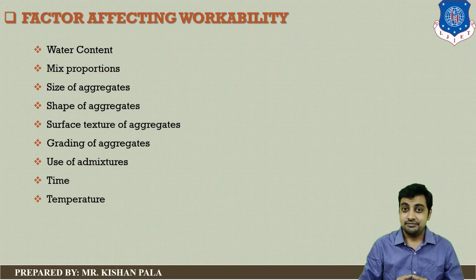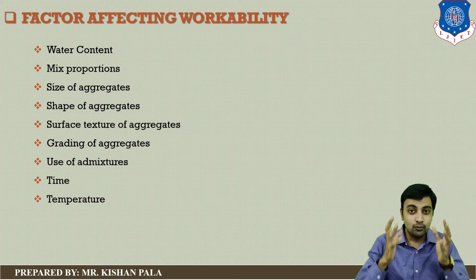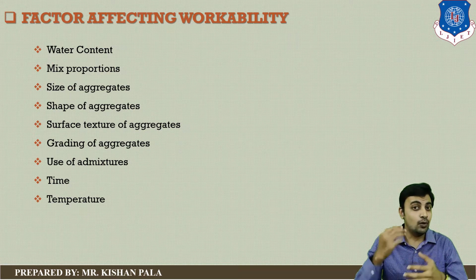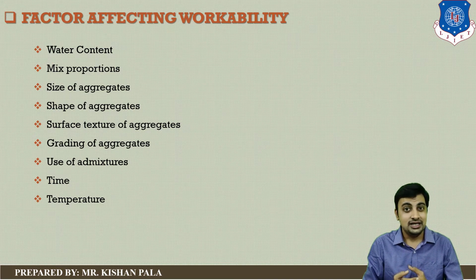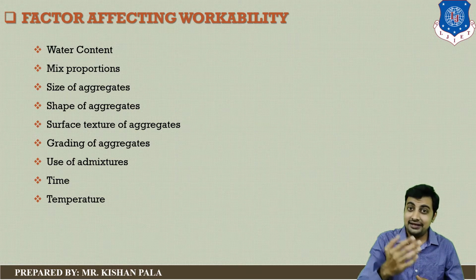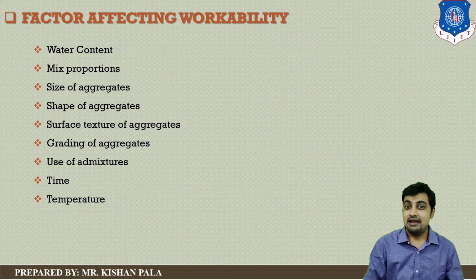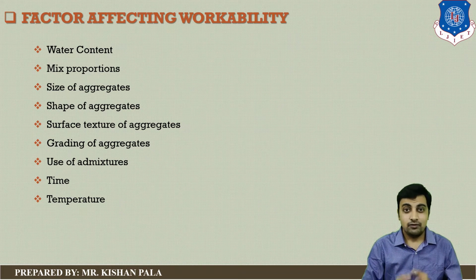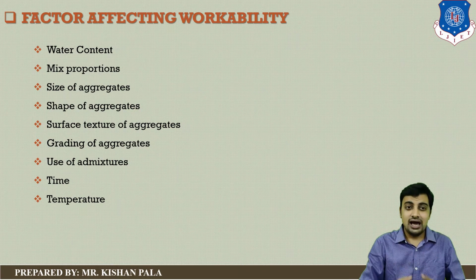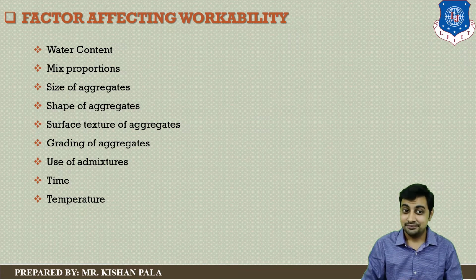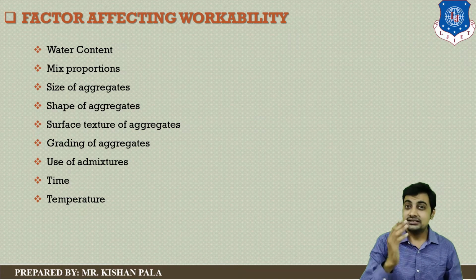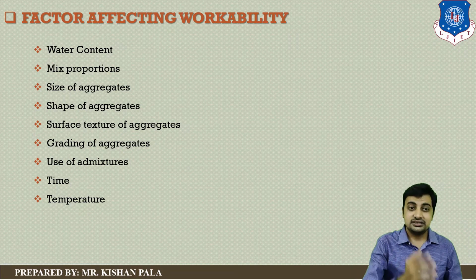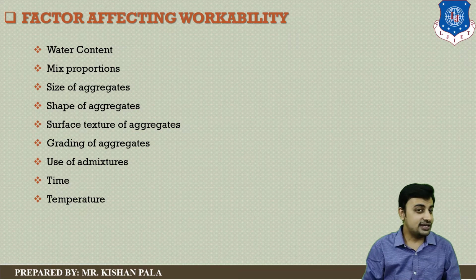Next point is temperature. With increasing temperature, the removal of water content will be high, and the decrease of the water mass will give you lesser workability. With high temperature, you will get lesser workability, and with low temperature, higher workability for a particular concrete mix. So these are all the important factors we should consider, because these affect the fresh property, the workability of the concrete mass: water content, mix proportions, size of the aggregates, shape of the aggregates, surface texture of the aggregates, grading of aggregates, use of admixtures, time and temperature.